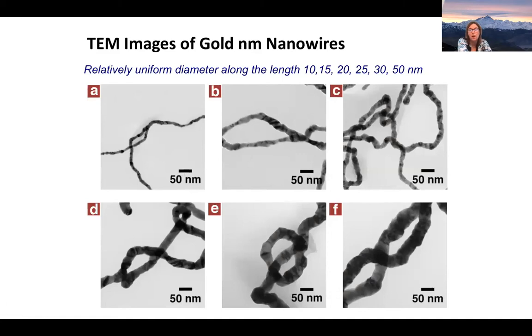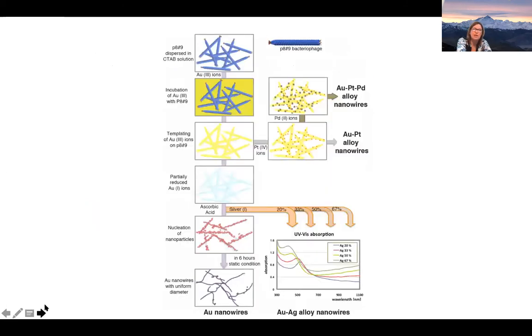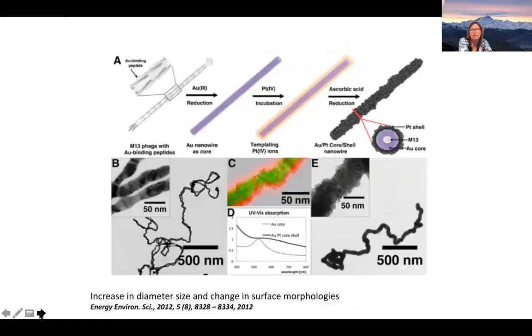So these are tiny wires that are gold. And so with different sequences, different chemical processing, we can control the diameter and length of these nanowires. And then we can actually start growing all kinds of different kinds of metal nanowires. So this is a gold, platinum, palladium nanowire, gold, platinum nanowires. We use many different kinds of combinations of these, and we've used it mostly for catalysis.